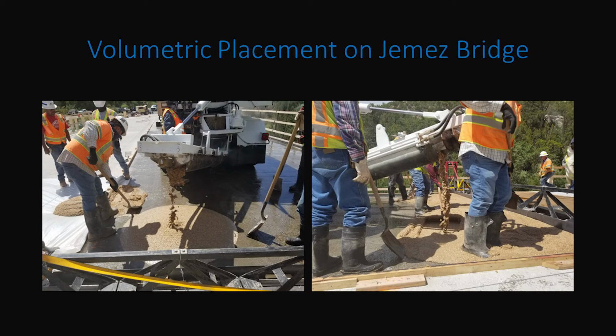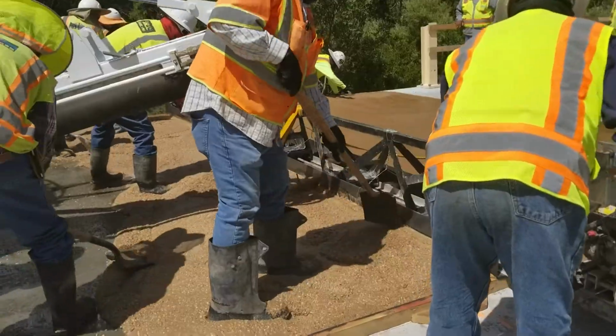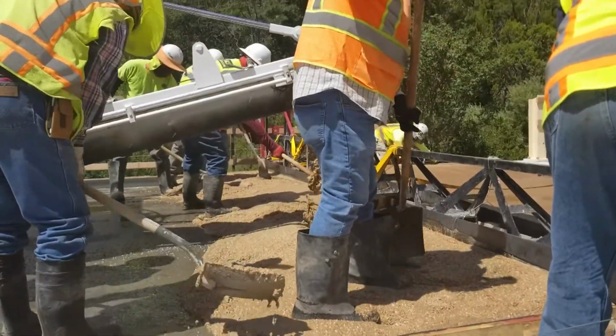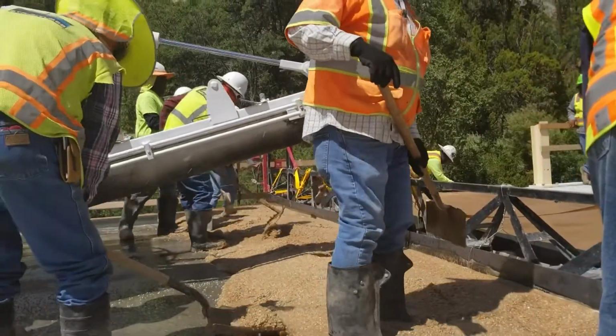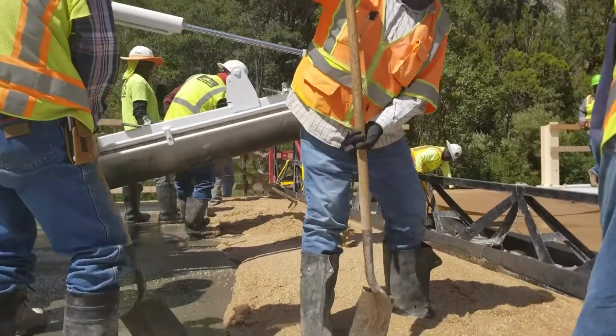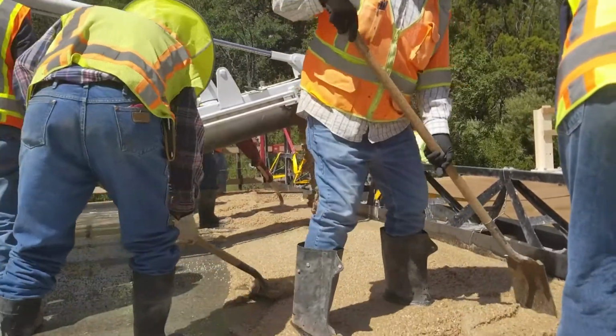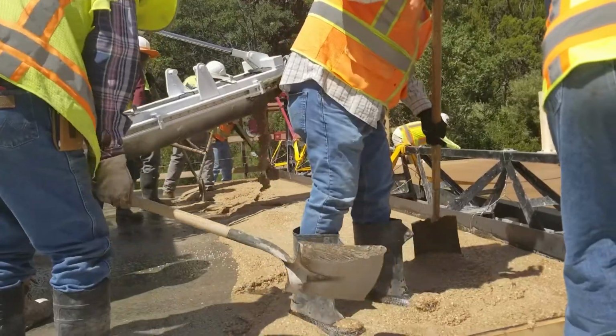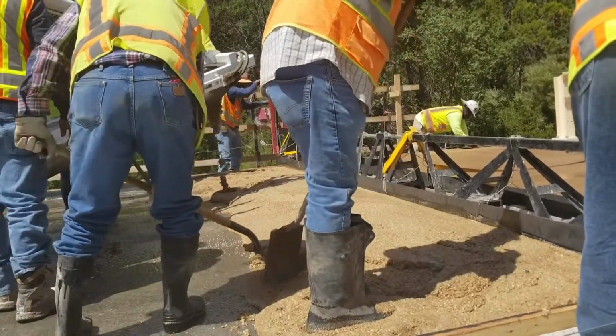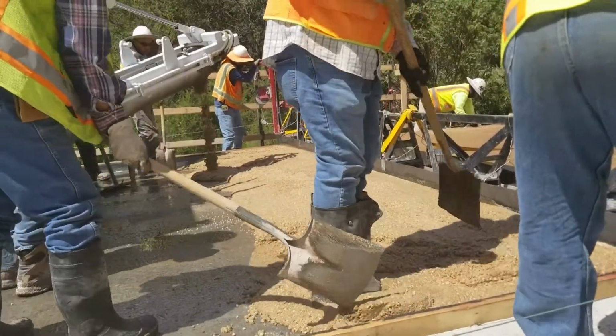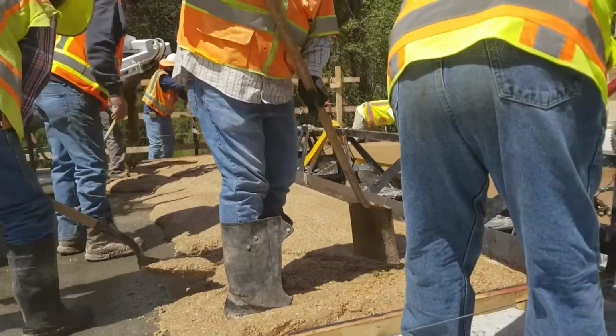A few pictures of the placing. The placement's very similar to Portland concrete placement. It's a higher slump product. It actually places and smooths very well. We use a vibrating truss screed. We want to make sure we get any of the air out of the material, and there's a resin that will float up to the surface, and we'll put a traction aggregate into that surface.